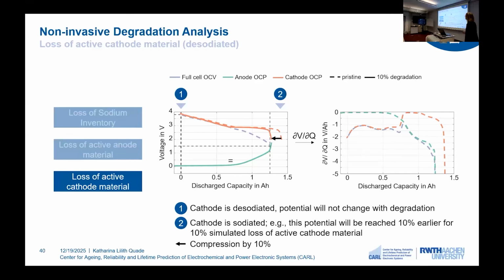And we can see here the anode OCP. This does not change because we only lose active cathode material. And we can see that the full cell voltage does change because our cathode OCP has changed. And because we're still cycling between 1.5 volts and 3.8 volts, we have a capacity loss because our voltage limits are reached earlier. And this capacity loss is visible here in gray. And now let's have a look at how this influences the first derivatives. Here we can see the shift of the first derivative of the cathode, and we can also see that the full cell voltage curve has shifted as well. And when we focus now on the middle part, we can see that the peaks here shift to the upper left.